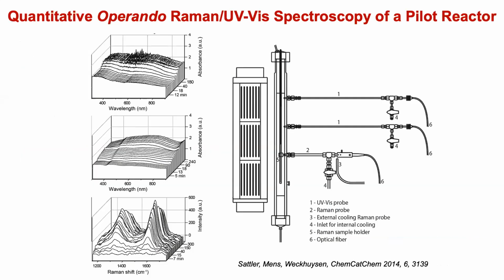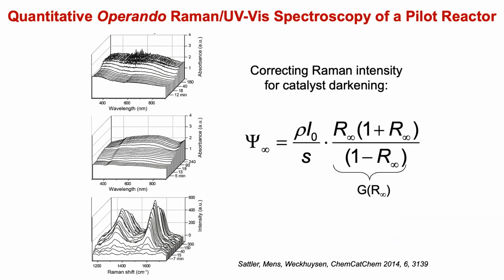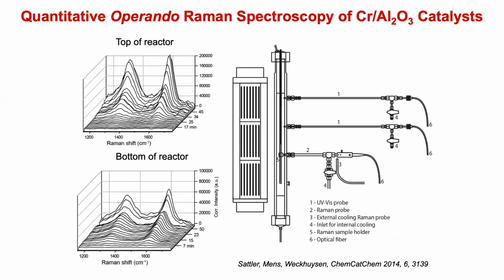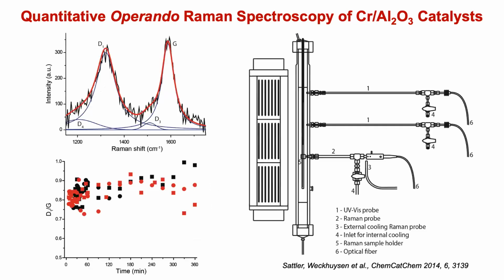So we were able to measure UV-vis, Raman, we correlated, we applied our formula. We have top of reactor spectra, bottom of reactor spectra, as you can see here, and they nicely increase. You see the coke deposit bands, the D and G bands, as we call them in coke, increasing on the left. You can also measure the type of coke in the reactor, but that does not change a lot. So I hope with this example, there's one addition.